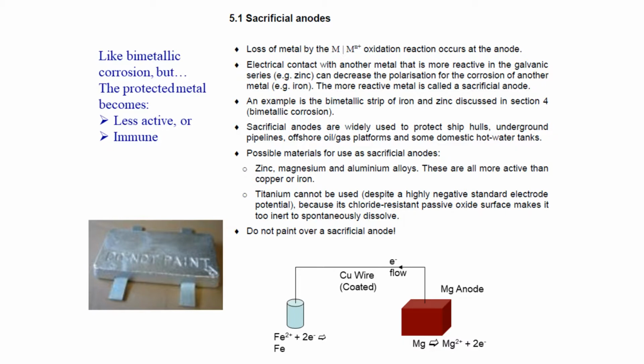One of the more amusing things you can do wrong, though, is that somebody can come along and see this poor suffering sacrificial anode dissolving away, and think: this part of the exposed metalwork seems to be the only really badly corroding part of the structure, so what I think I will do to improve the situation is apply some corrosion protection - but we only need to apply it to this bit. So I'll paint over the sacrificial anode, these people say. And when they do that, of course, this removes the useful corrosion protection it was providing, and the rest of the structure is no longer protected.